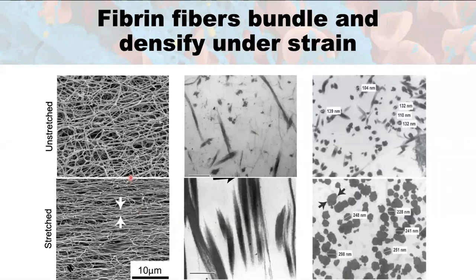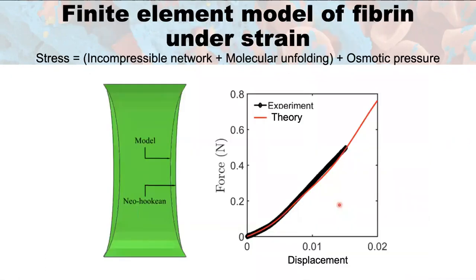Using scanning electron microscopy, we're able to see the same phenomenon with the bundling or densification of fibers under strain. Here you can see that the fibers are further apart, whereas here under stretch samples, you can see that not only are they aligning, but they're coming closer together. We're also able to use transmission electron microscopy, where we can look and see the alignment of fibers here in unstretched samples and here in stretched samples. We can see alignment of fibers and the increasing of the diameter of these fibrin fibers, showing the bundling of the fibrin fibers under strain. So that helps to tell us some about the structural changes that are happening.